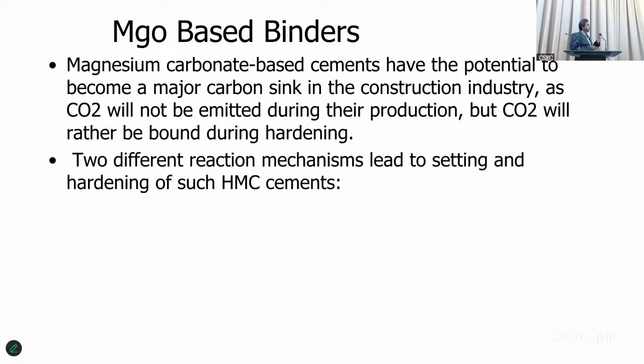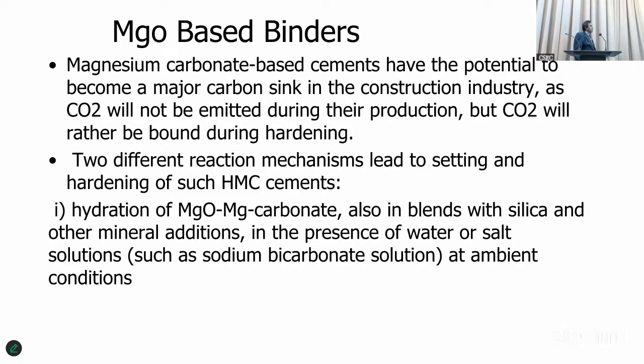This is very important. In this case, the CO2 magnesium carbonate based cements, which are going to come to the world, have the potential to become a major carbon sink. There will be two different reaction mechanisms for setting and hardening of such cements. The first is hydration of magnesium oxide and magnesium carbonate, also blending with silica and other mineral additions, in the presence of water or salt solution at ambient temperature. So this is the main way of hardening.